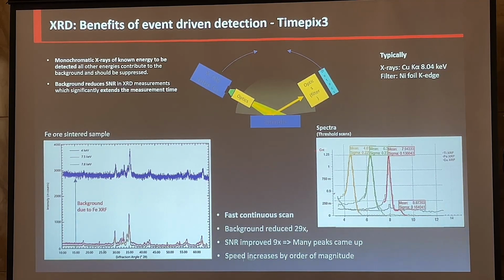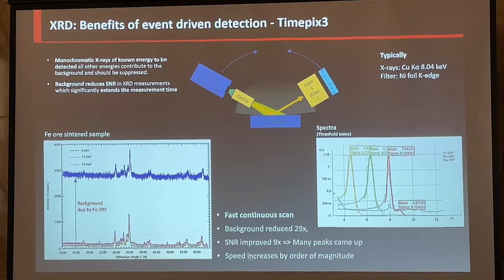These detectors of ours have a nice feature because they are spectral, so we can select a certain energy band. And since we know that this is very often an X-ray tube with a copper target, people are detecting fluorescence of copper, which is 8 kiloelectron volts. So we would like to select only 8 kiloelectron volts, which is this red peak here, the K-alpha of copper. If we do such a thing, then the background in this measurement drops by a factor of 30. Then the SNR is improved by a factor of 9, and you start to see even peaks which are very difficult to see in the original measurement. So either you would have much higher sensitivity, or you can make a much faster scan, increasing the speed of the scan by a factor of 10, in fact, reducing it from half an hour to 3 minutes, which is pretty big.